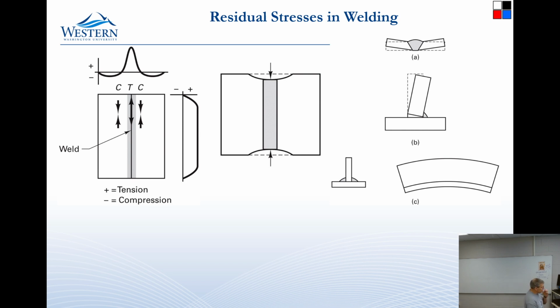When we did the 3D printing with the welding, we would draw one line of weld on a 1/2 inch thick plate of stainless steel, and it would potato chip more than 1/8 of an inch for just a piece that was about 8 inches by 8 inches. There was nothing we could do to bring it back. We tried doing a little bit on the front and flip it over and do a lot on the back. Didn't matter. If you had touched the front, it would potato chip. So to get around this,